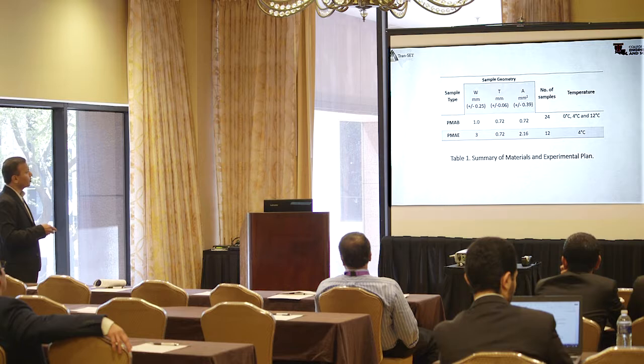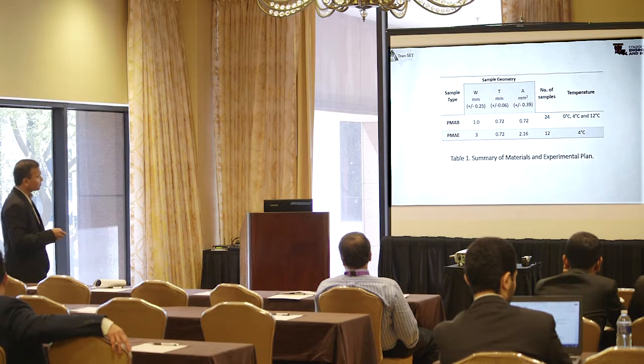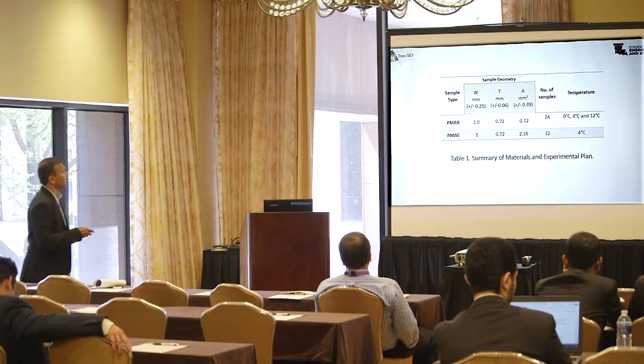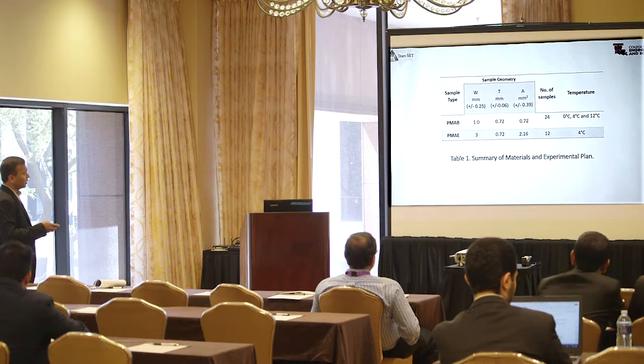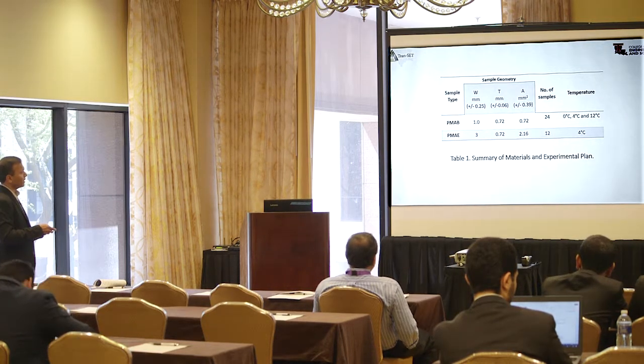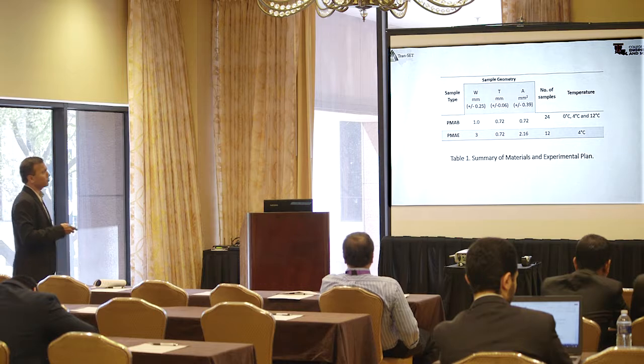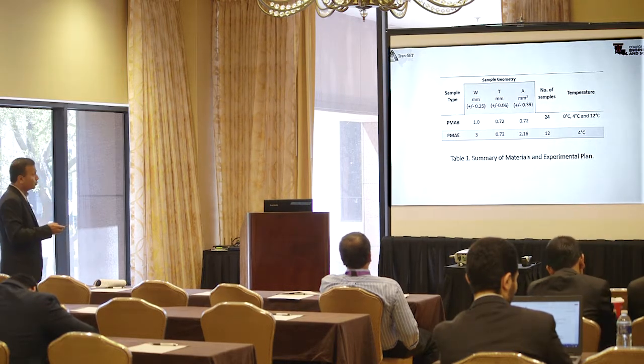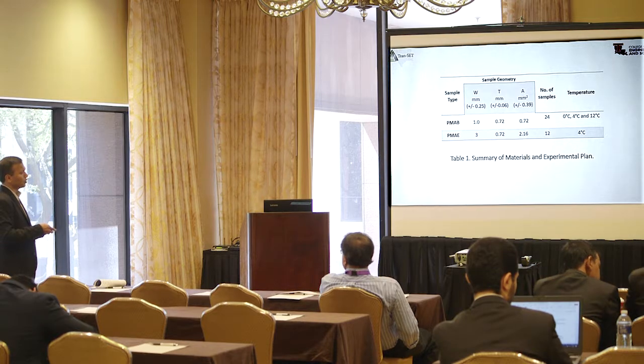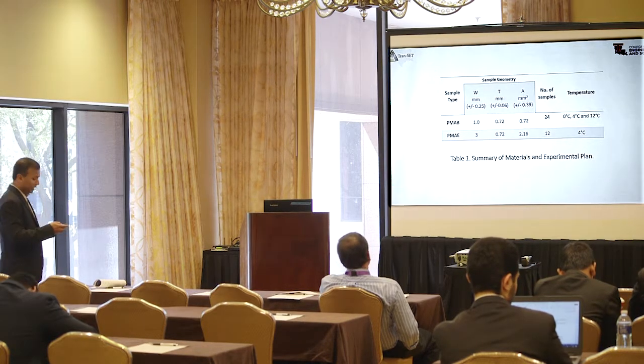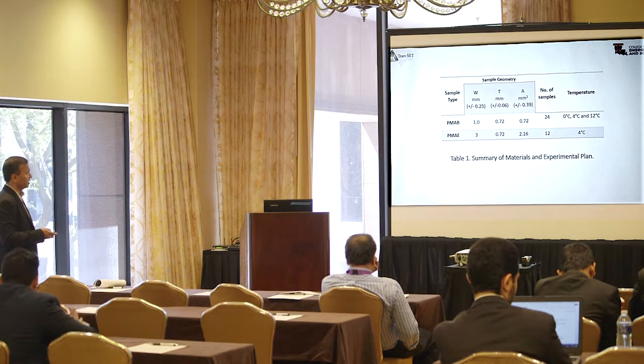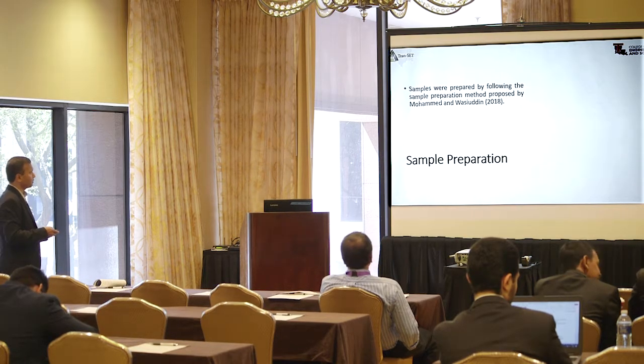And here for modified binder, we have 3 temperatures, and for each case we use actually 3 samples. So that's why here you should have 27. The reason we have 24 instead of 27 samples is that we could not do the PAV aged sample at 0 degrees Celsius, because it is very stiff for doing the extensional test. So that's why instead of 27 we have 24 samples here.